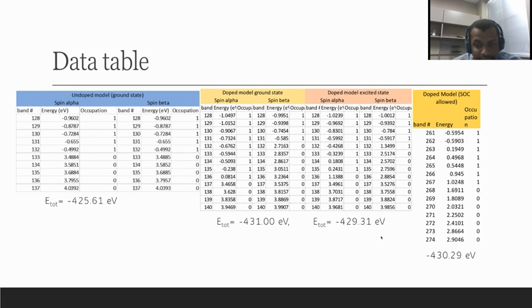So that would be described as a density of states that's not symmetric, and the crystal field theory also predicts that these 5 electrons contributed by the manganese would have higher energy than they were supposed to have, and these higher energies are here in this table.